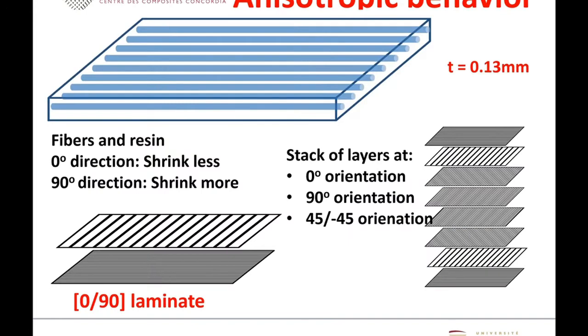So basically, that is the 4D, the fourth dimension. The fourth dimension is that you start with a flat layer, then after that you cool it down, and then it gives you the curved configuration. So that's basically the idea in terms of the mechanism behind the 4D printing of composite. It depends on the anisotropy, that means the difference in the properties along different directions, to create the change in the shape of the structure. And at the beginning, you only need to have a flat mold. You lay everything down flat to begin with.